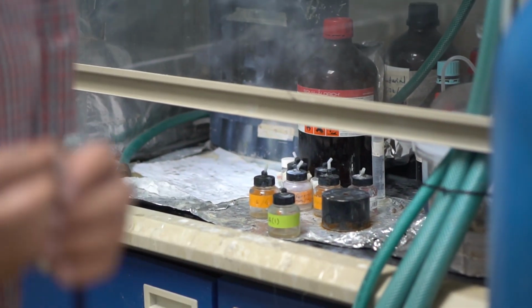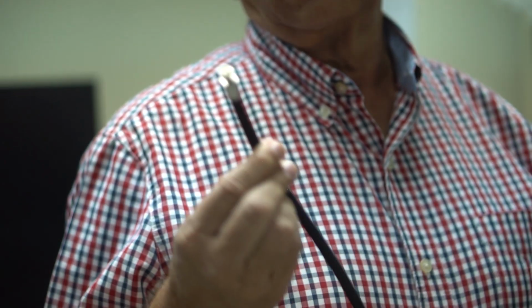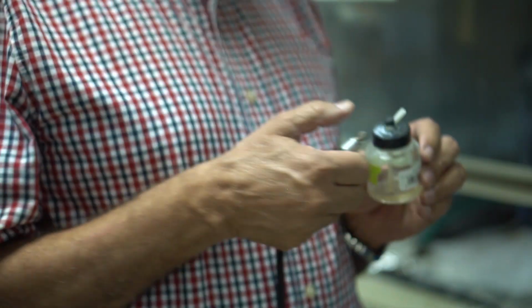Okay, here we make those surfaces which we talked about, for oil-water separation, and we use a very pressurized gun. We have a very fine gun of, let's say, a few micron size. We put it here, we put pressure, and we put the material which we like to coat on those substrates, and then we can put a substrate and make a film as good as possible to use for oil-water separation. And this separation we actually study through two properties, what we call hydrophobic, hydrophilic, oleophobic, oleophilic. Anything philic means it loves water. Anything phobic means it is afraid, so it repels water.